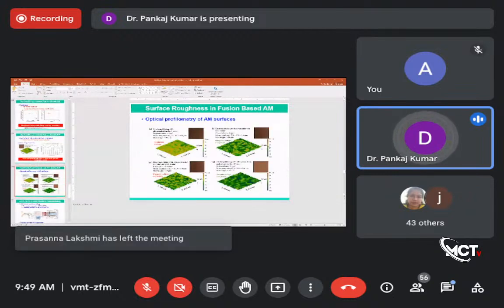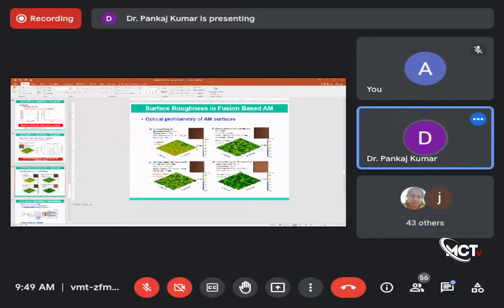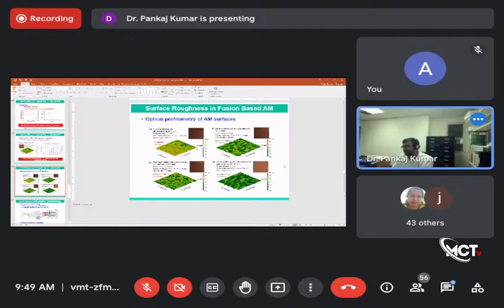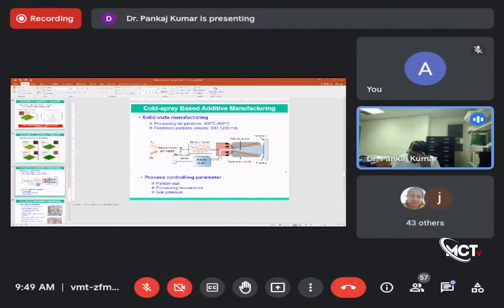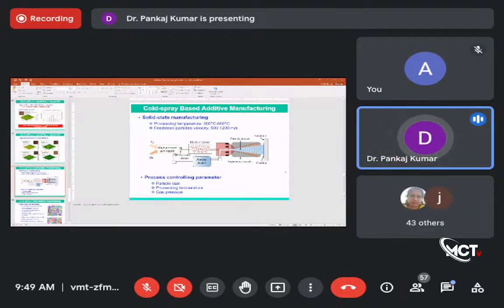With different parameters, we are able to get a very finished surface. The mean surface roughness was reduced from the initial 10 microns to 2.2 microns. So that is a significant difference, right? Okay, so those are the different challenges with the fusion technique. You have the microstructure challenges, the surface roughness challenges, and the processing challenges.